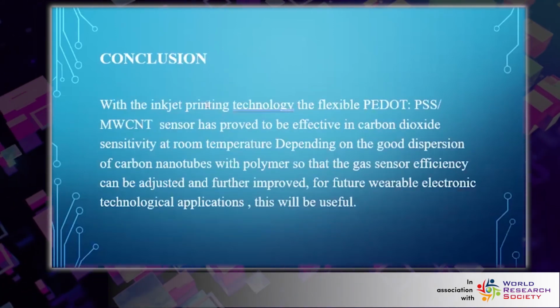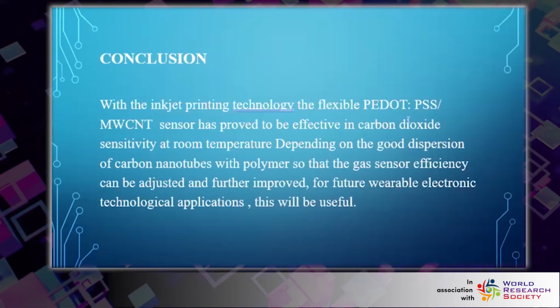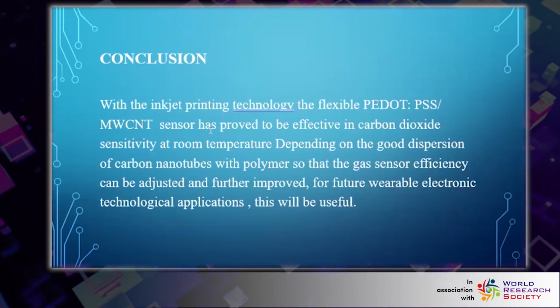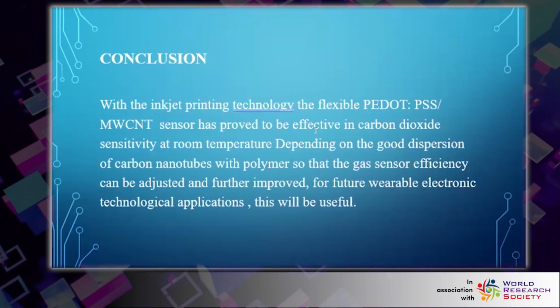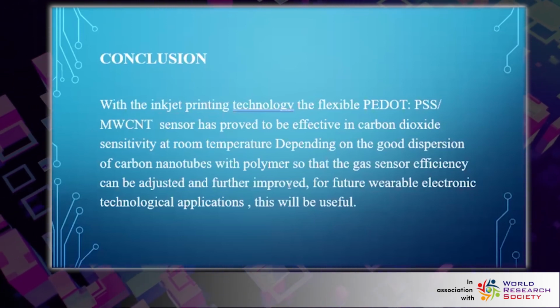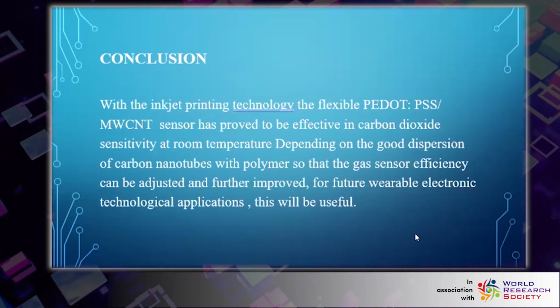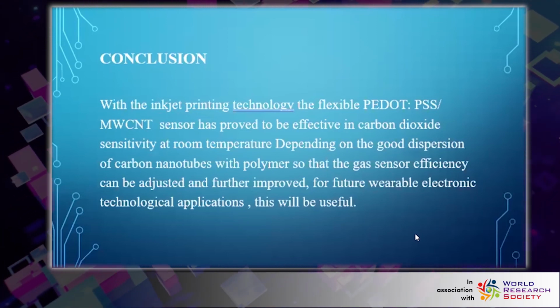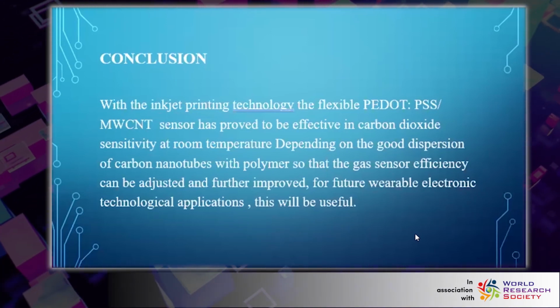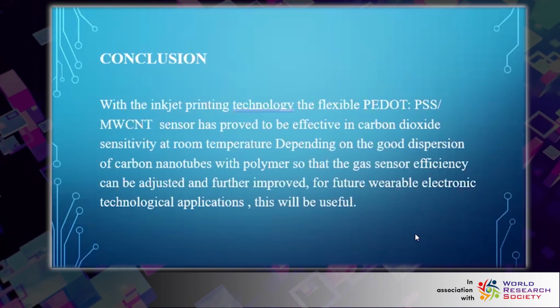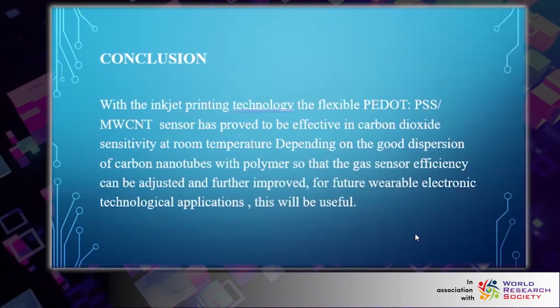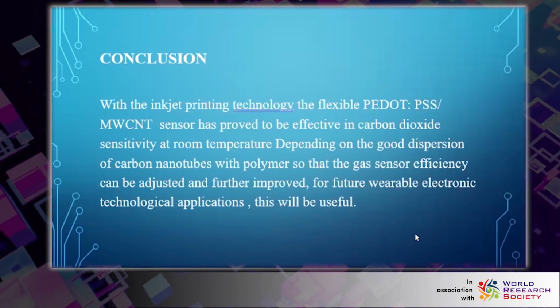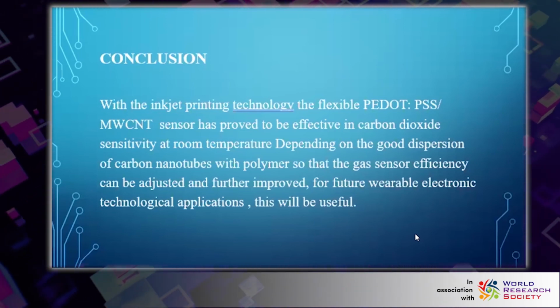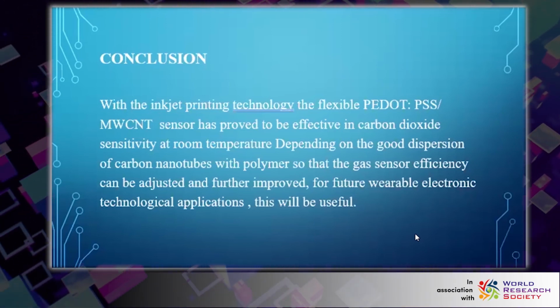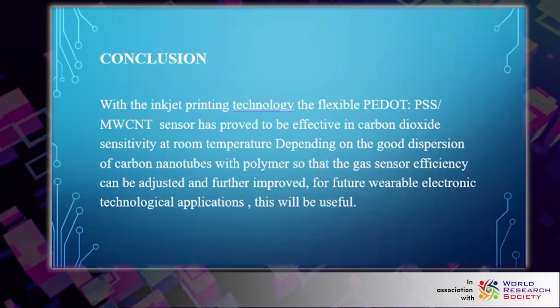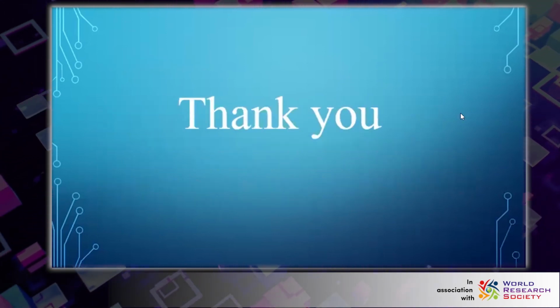Conclusion: with inkjet printing technology, the flexible PEDOT:PSS multi-walled carbon nanotube sensor has proved to be effective in carbon dioxide sensitivity at room temperature, depending on a good dispersion of carbon nanotubes in the polymer, so that the gas sensor efficiency can be adjusted and further improved. For future printed electronics technology applications, this will be useful. This is the last thing.